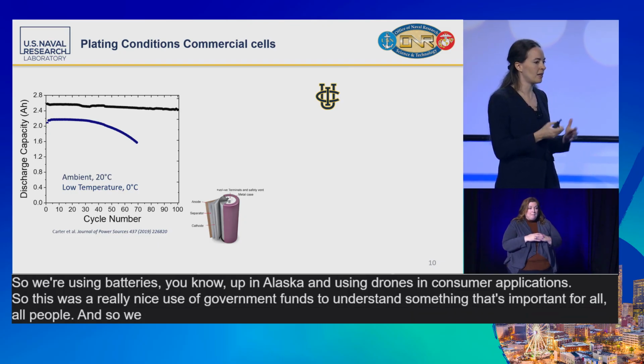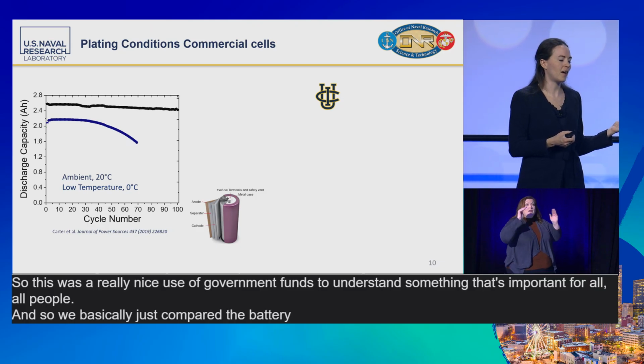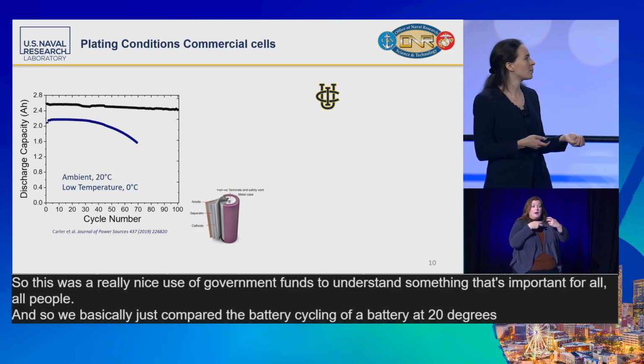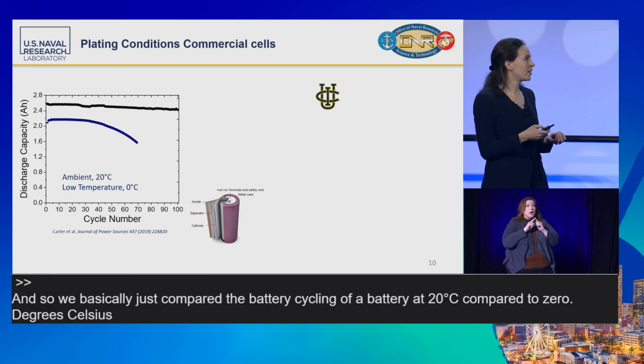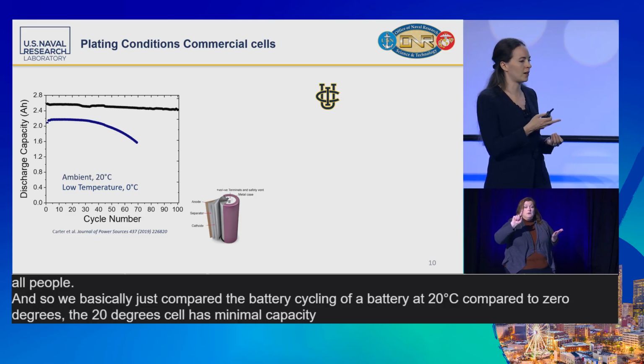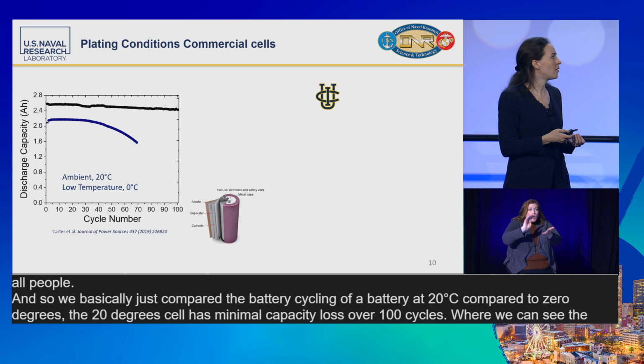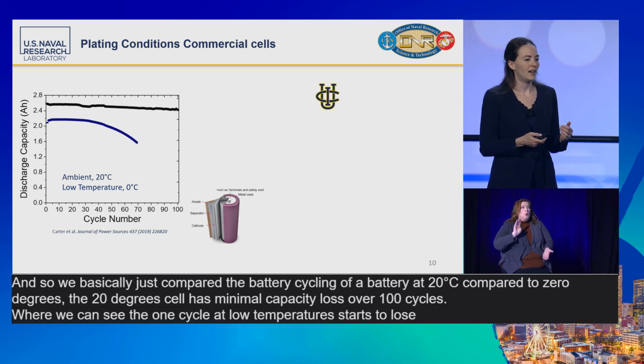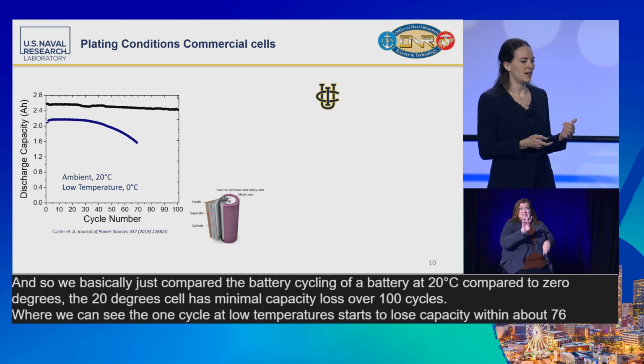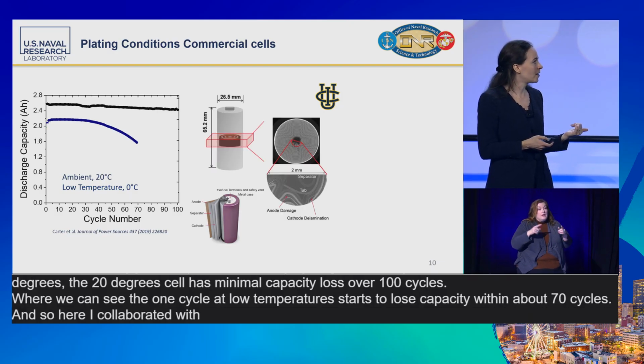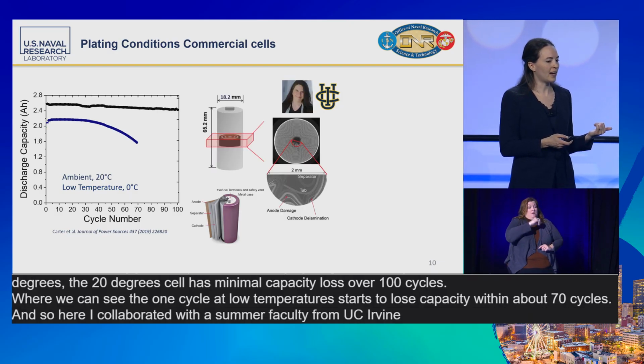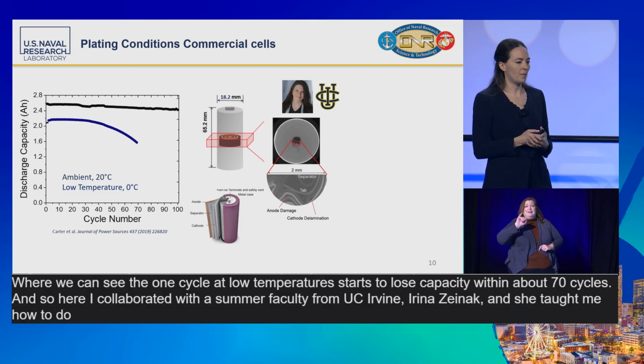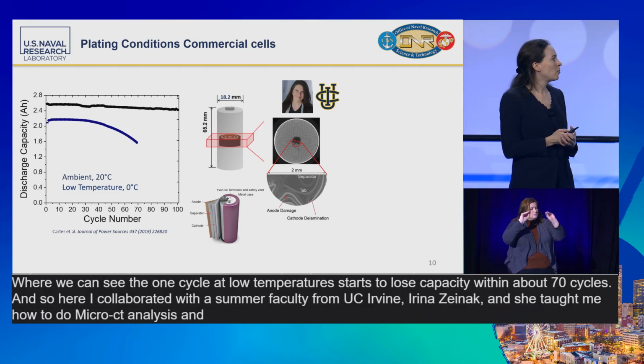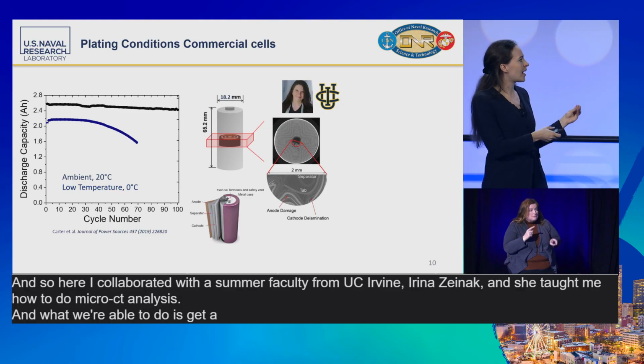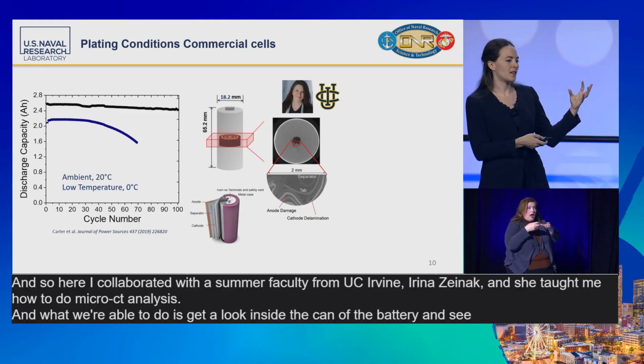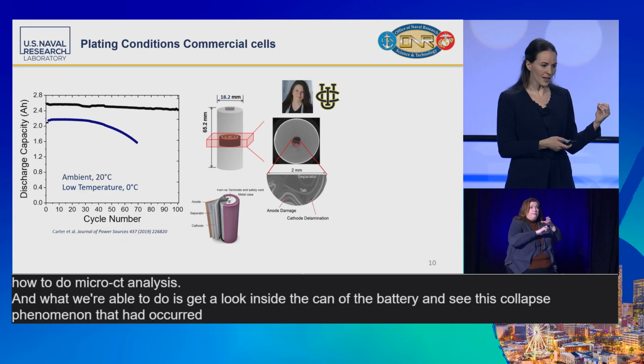And so we basically just compared the battery cycling of a battery at 20 degrees Celsius compared to 0 degrees. The 20 degrees cell has minimal capacity loss over 100 cycles, where we can see the one cycled at low temperature starts to lose capacity within about 70 cycles. And so here I collaborated with a summer faculty from UC Irvine, Irina Zenyek, and she taught me how to do micro CT analysis. And what we were able to do is get a look inside the can of the battery and see this collapse phenomenon that had occurred into the core of the battery.